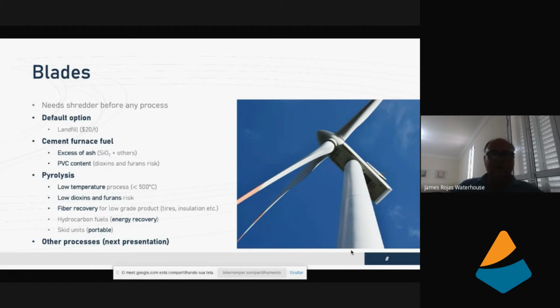So maybe the cement factories, instead of purchasing the material, will charge you to use these materials and neutralize them. And you're going to waste the whole fiber content just because you're going to melt it. The cement furnaces are high temperature furnaces. That's good news. The bad news is most of the blades, almost all the blades, contain PVC foam inside, and PVC contains chlorine, and chlorine with the temperature and carbon forms dioxins and furans. That's extremely toxic for human life, extremely toxic. So a small amount of PVC is going to generate a massive amount of dioxins and furans at high temperatures and in uncontrolled burning. So this is another huge problem for this type of material.